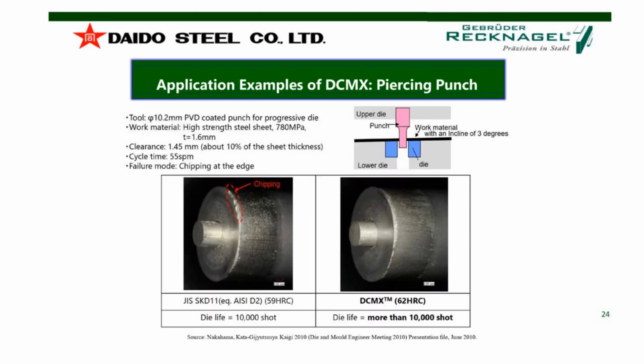So let's take a look at some examples for DCMX. In this picture, we have a piercing punch. The customer was using standard D2 grade at first. And as you can see in the picture on the left, the customer has the typical problem of chipping at the cutting edge. He was using D2 with 59 HRC, and his tool lifetime was about 10,000 cycles. And then he used DCMX for the first time with a higher hardness of 62 HRC, and tool lifetime was more than 10,000 shots without chipping. I guess in the end it was wear resistant. Next, please.